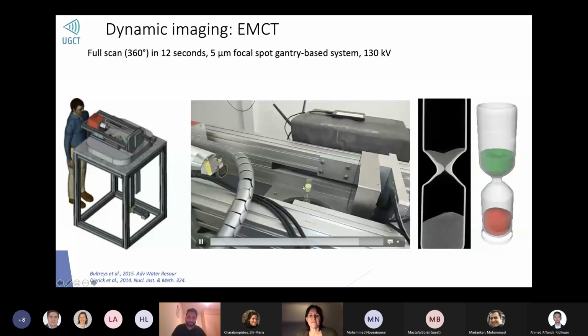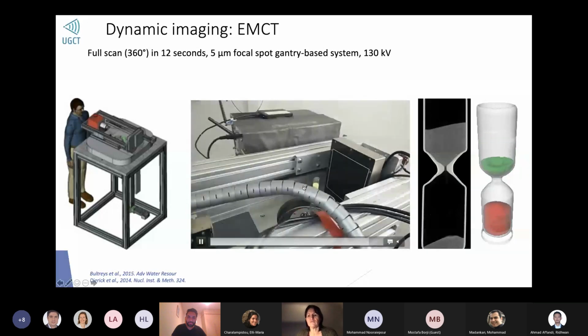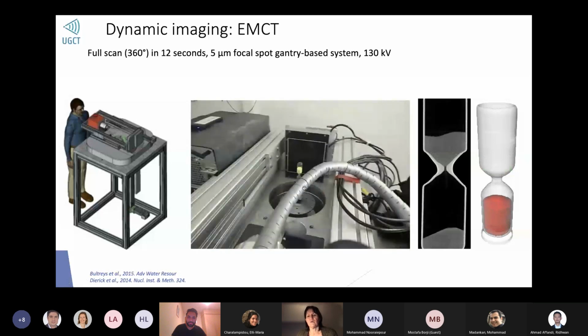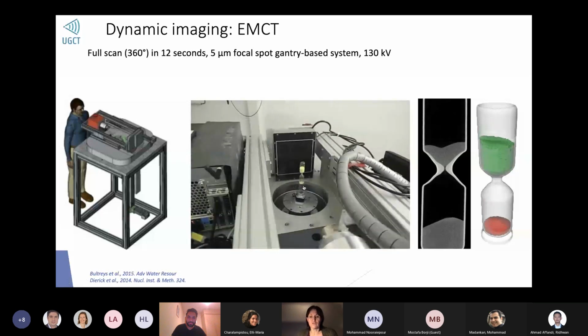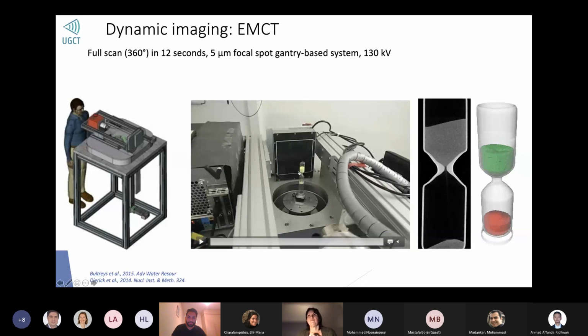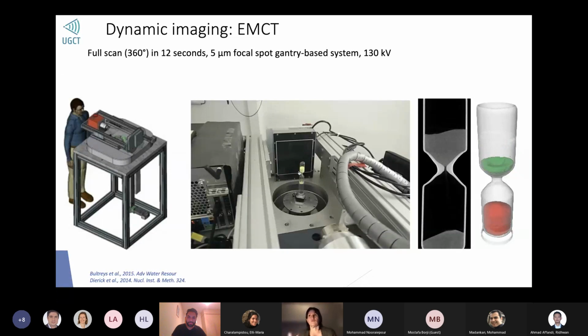Now we have a system where the source and detector are rotating instead. This is because if you want to control dynamic processes, with sensors for temperature or flow lines connected to your sample, it's sometimes easier if this is stable rather than having to rotate continuously for 20 minutes in a fast way. So we built a scanner where the sample and the entire setup are stable.